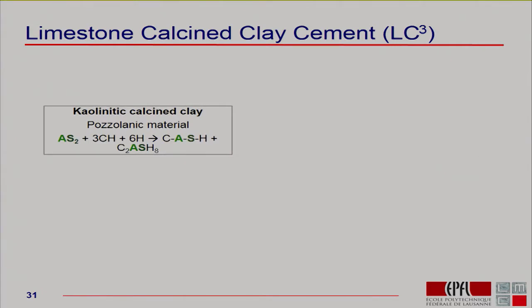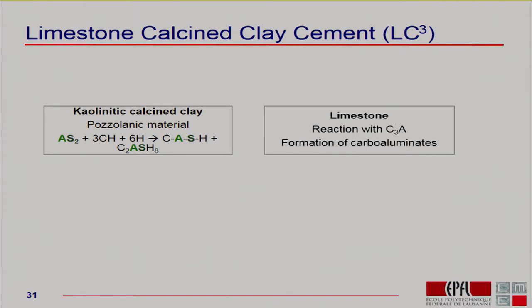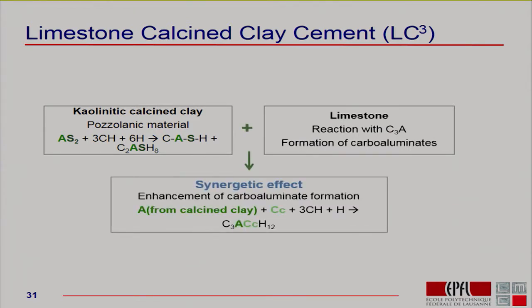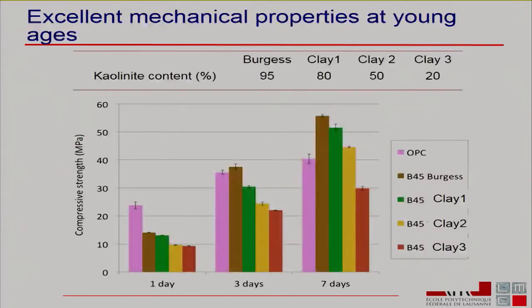And of course we've done the analysis behind it. We know what's going on in terms of chemical reactions. Sorry, this is in cement chemist notation, where A is alumina oxide, S is silica, etc. We have alumina and silica coming from the clay. We know they can react with calcium hydroxide, which is produced by the clinker, to produce CSH and other alumina phases. We know that limestone can react with alumina. Well, we put the two together, and we can get a lot of this phase, which we call calcium monocarboaluminate. And this is a hydrate like any other hydrate. It fills space. It bridges the gaps between those grains.